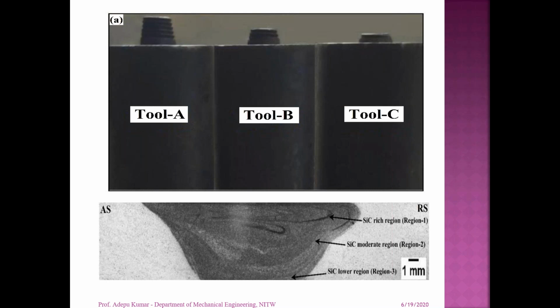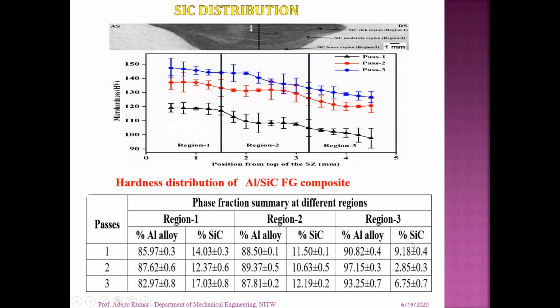In region 1, the aluminum content is like this, and the silicon content is 14.03 plus or minus 0.3, 12.37 plus or minus 0.6, and 17; region 2 is 11.50 and 10.63 like that, and region 3 is 6.3. So region 3 has the lowest silicon carbide percentage, region 2 is a little higher than region 3, and still higher is region 1. You can also conduct a hardness survey from top to bottom, and the hardness varies from region 1 to region 3. Region 3 is the lower one, region 2 the middle one, and region 1 the top one. The top has almost 14 to 17% silicon carbide, region 2 only 10 to 12%, and region 3 only 2 to 6%.